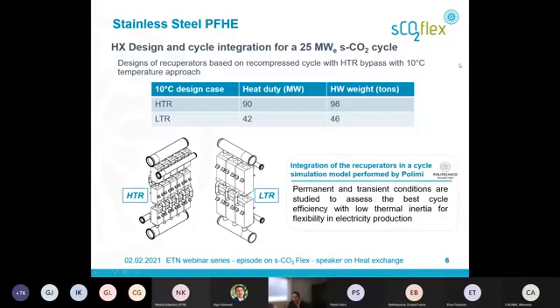So I present an option with 10 degrees C pinch. The heat duty for the HTR was 90 megawatts, and for the low temperature it's about 40 megawatts. So the design, we have an estimated weight of around 100 tons for the HTR, not too far from 50 tons for the LTR.